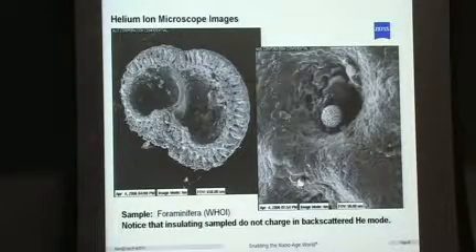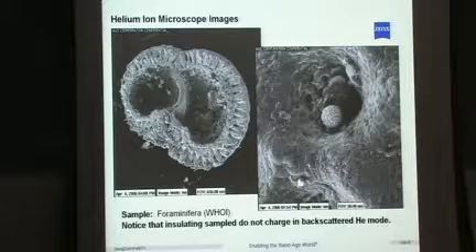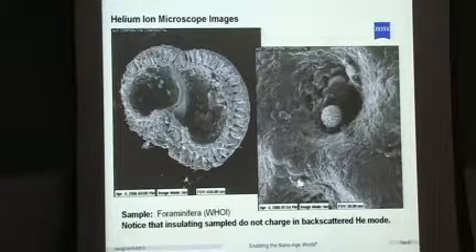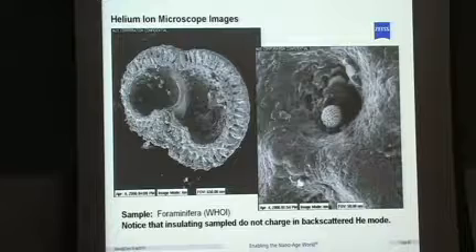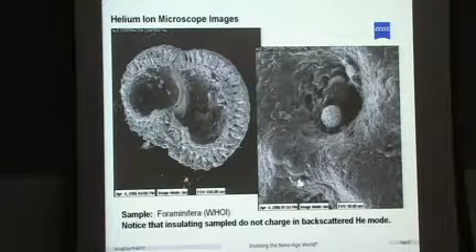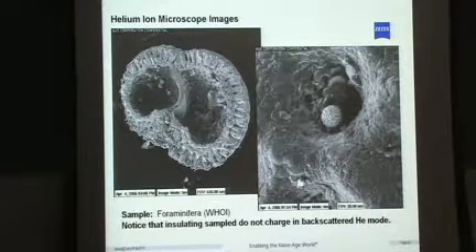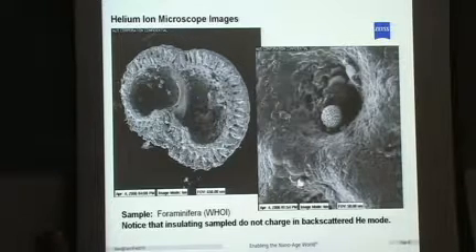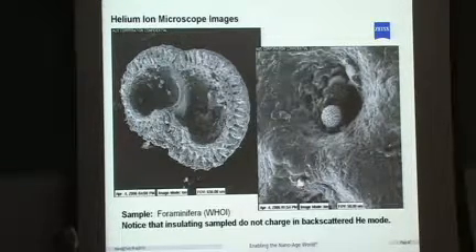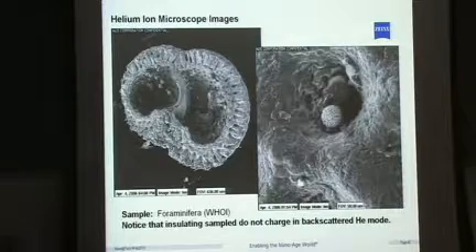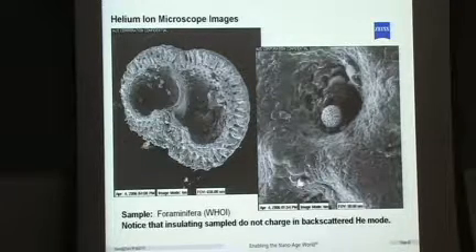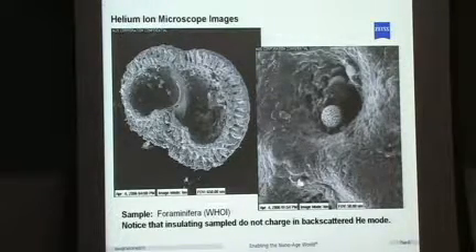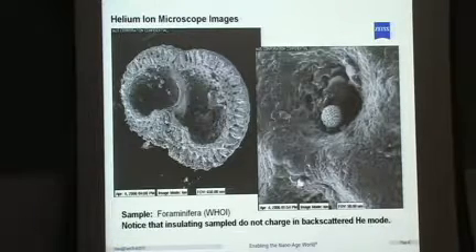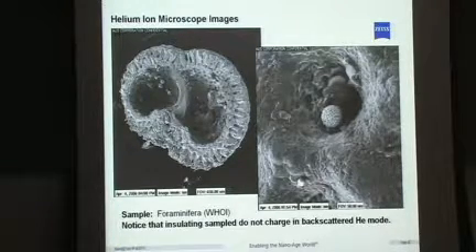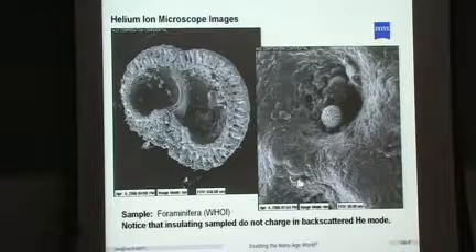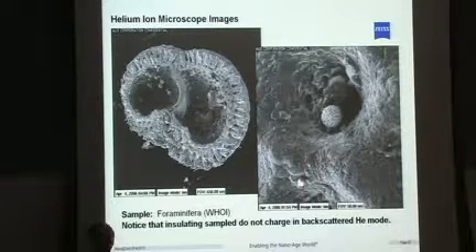This is a fairly old image from when we first got the tool working, but it showed us right away that we had something unique. This is a foraminifera from Woods Hole Oceanographic Institute, little dead skeletons of creatures that lived a long time ago, I guess. But we found we didn't have a charging problem. The helium beam interacts in a very different way than an electron beam, primarily because as the helium beam hits, being quite greedy, the helium ion grabs an electron from the substrate right away and continues on the rest of its trajectory in a neutral state.